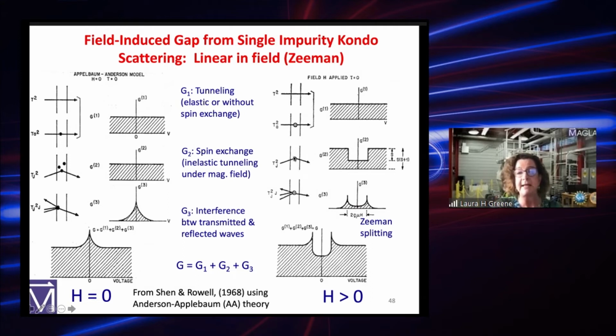Now, if you put a magnetic impurity in the interface or near the interface, then you open up a new channel for scattering across the junction. And what happens then is that you have an easier way for the electrons to get across. When you give them enough energy that they can flip the spin in or near the barrier, they have a new channel to get across. And then you get an increased conductance when you increase the energy of the bias. And so you get a splitting here. It looks like a splitting, but it's actually increased conductance outside of the Zeeman splitting. And that increases linearly with field.